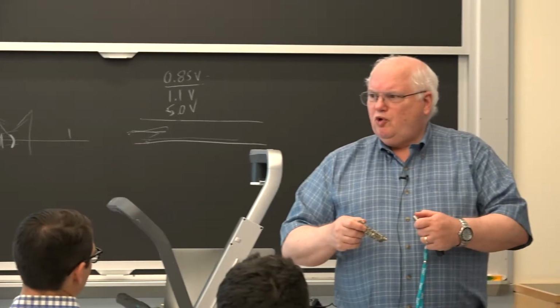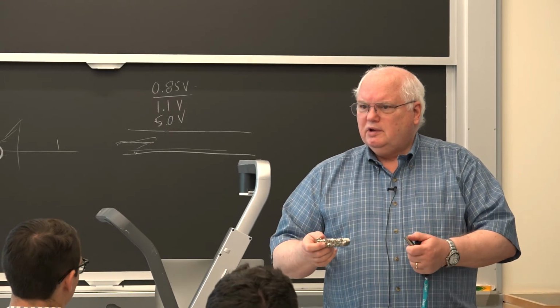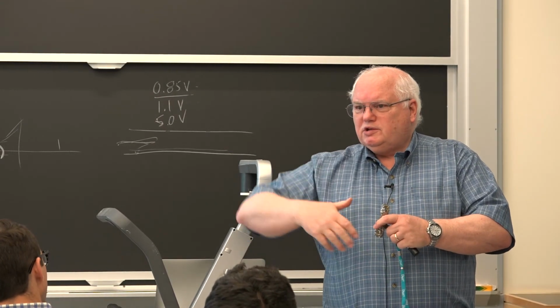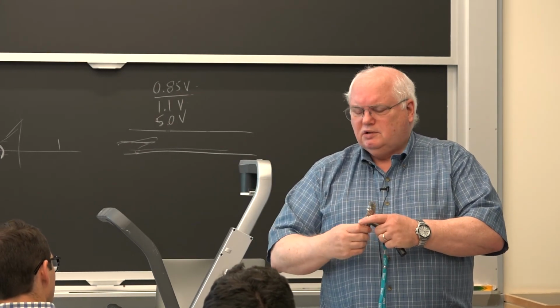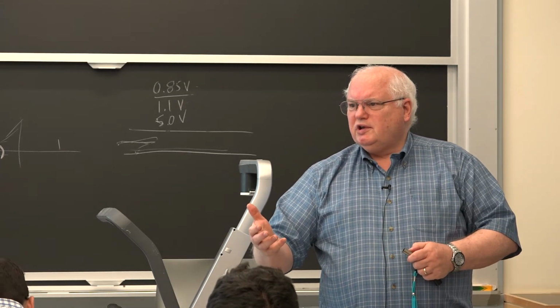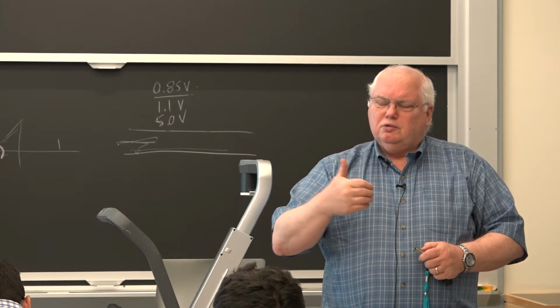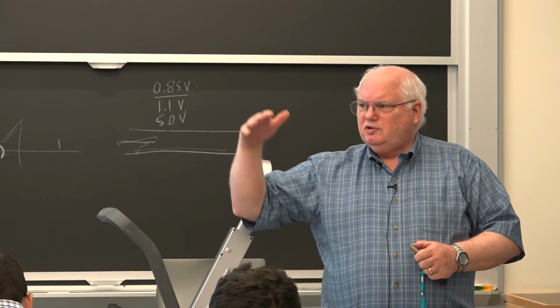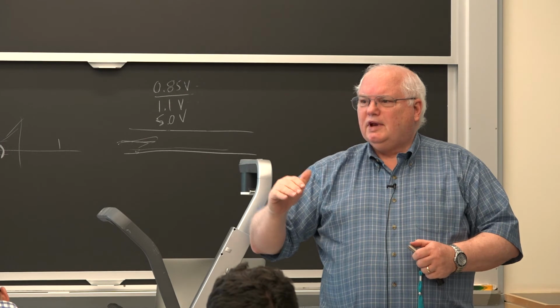introduce zirconium chloride or titanium chloride gas, which at like 300 or 400 degrees is a gas. It comes in, it sees the hot wire, it decomposes, and gives you chlorine, which you use to rechlorinate some more zirconium oxide and stuff, and you end up forming crystals. It's a vapor deposition process, decomposing the zirconium chloride into zirconium crystals, and you get crystals because you have a big entropy change when you go from the vapor phase to the solid. And that gives you crystals.